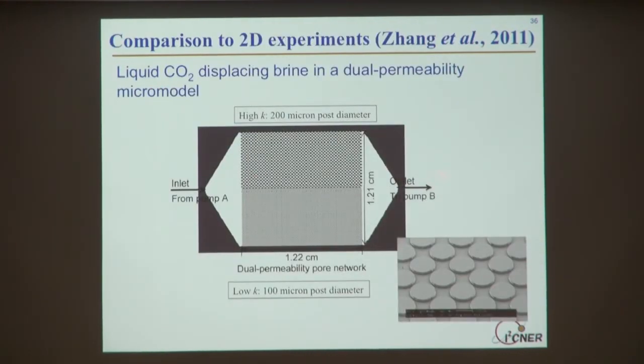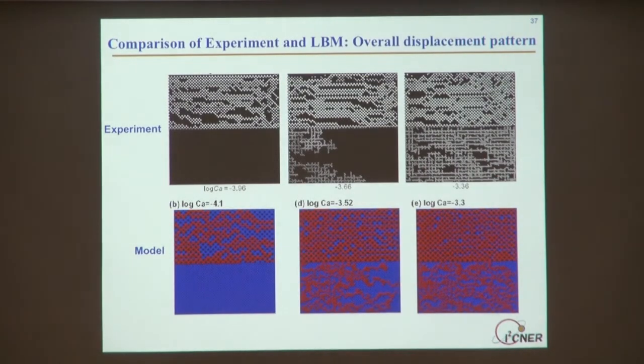So here is an example model, micromodel, porous structure, where you have low permeability, high permeability on top, low permeability on the bottom. Here's the porous structure, again, very similar to what I showed you before. They've done experiments with actual supercritical CO2 migrating through this structure, and they've also done numerical simulations under the same conditions. And this shows at least qualitative comparisons. So on the top are the experiments for various capillary numbers, and these are the overall displacement patterns. So white regions are where CO2 has migrated. Okay? And you see quite good qualitative comparison between the experiments and the model. And the idea here is to do more quantitative comparison that allow fine-tuning of the model to actually predict quantitatively the characteristics of the experiments.